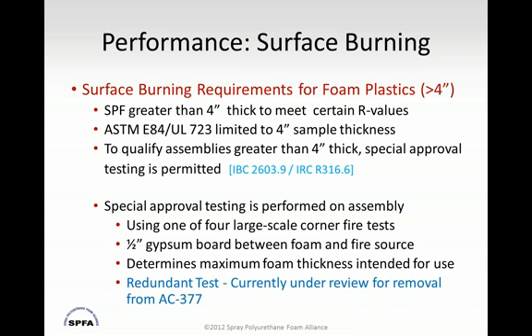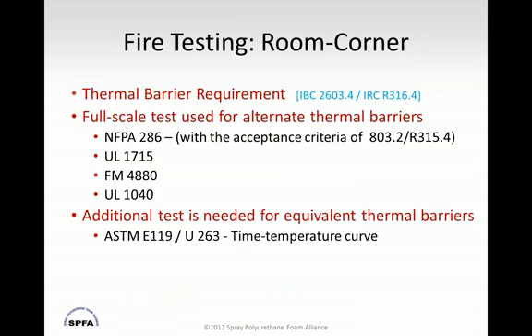In fact, we've done these at a wide variety of thicknesses of foam, and the thickness of the foam, once you're beyond 4 inches, also doesn't seem to affect the test. So in many cases, we see that it's a redundant test. All it's really proving is that half-inch gypsum is a good 15-minute thermal barrier. So there's been a proposal to actually remove this requirement from AC 377. That's under consideration right now.